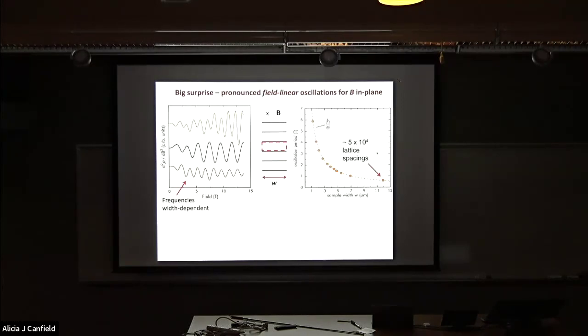And if you're going out to that thick one where we still see oscillations, that's about 50,000 lattice spacings. In microscopic terms, that's an extremely wide sample. And yet somehow we're getting a coherent effect. I think nobody could argue that that's not a quantum coherent effect which is causing that.